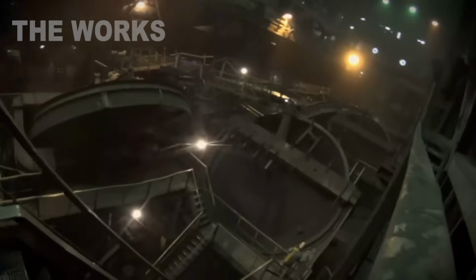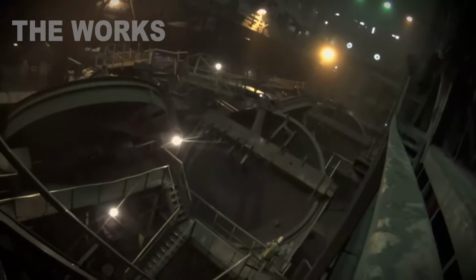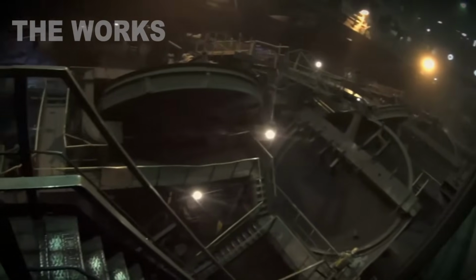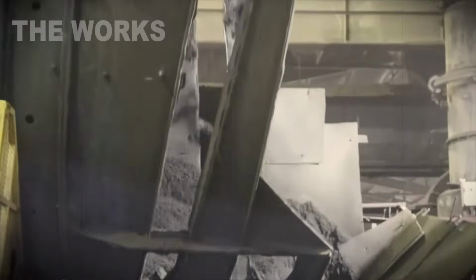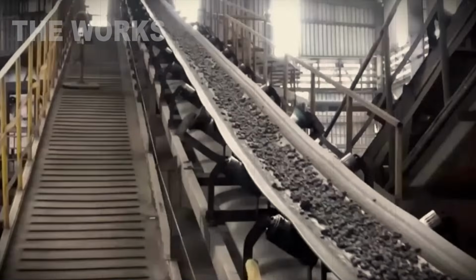Pelletizing. The concentrate goes to a disc pelletizer. The disc is 15 feet across, tilted at 45 degrees, spins at 15 revolutions per minute. Powder feeds onto the disc. Water's added, 3% by weight. Centrifugal force rolls the powder into balls. Pellets come out ½ inch in diameter, give or take 1/16 of an inch.